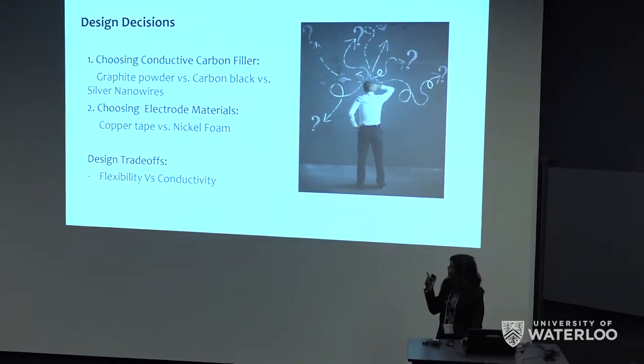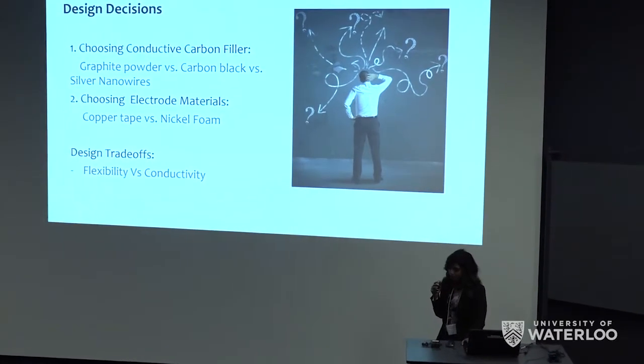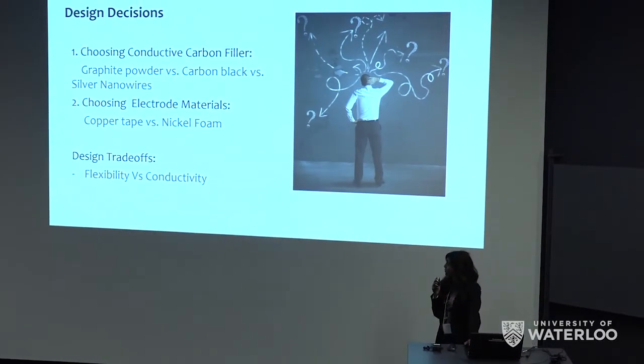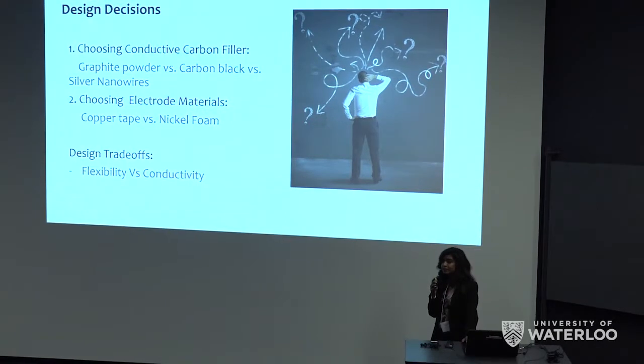Finally, I'm going to talk a little about the design trade-offs. One of the trade-offs that we faced was flexibility versus conductivity. Flexibility, as mentioned earlier, is brought about in our composite by PDMS, while conductivity is brought about by the conductive element, which was our graphite powder. However, increasing conductivity by loading of the material results in a decrease in flexibility. We finally optimized these parameters and settled on a loading of 40% to ensure that both flexibility and adequate conductivity were met by our material.